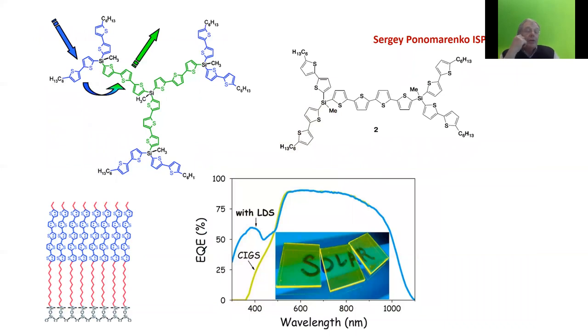There's another example of branched structures where I go a little bit to the functionality. When you link, in this case, these conjugated thiophene units, shorter segments to longer segments, the shorter segments absorb light in the more bluish range of the visible light and transfer the energy to the longer segment, which emits the light in the greenish range. And what is the result? You can make an antenna molecule, which over a large area takes up photons and emits them in a relatively narrow band at the core or at a defined place. It's a very important principle for the light harvesting complex in nature.